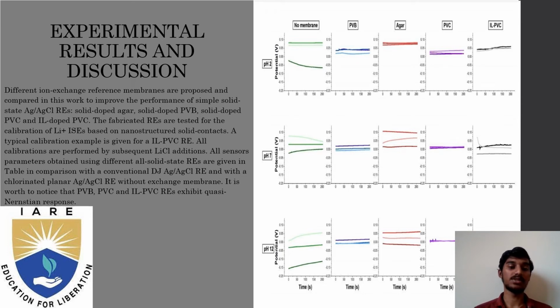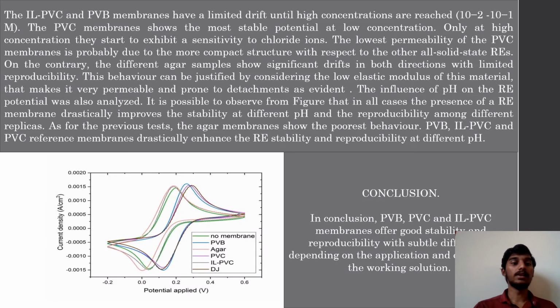In comparison with conventional DJ Ag/AgCl RE and with a chlorinated planar Ag/AgCl RE without ion exchange membrane, it is worth noting that PVB, PVC, and ILPVC REs exhibit quasi-Nernstian response. The ILPVC and PVB membranes have a limited drift until reaching high concentrations, for example 10 to the minus 2 or 10 to the minus 1 M. The PVC membrane shows the most stable potential at low concentration. Only at high concentration do they start to exhibit sensitivity to chloride ions.